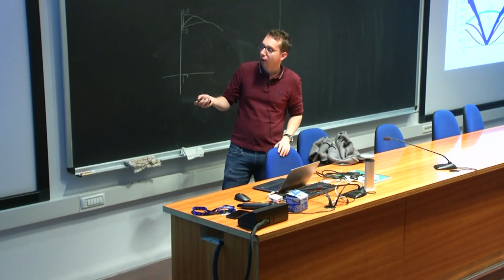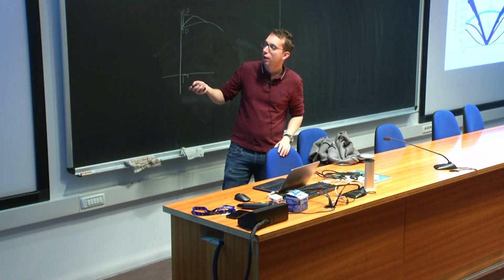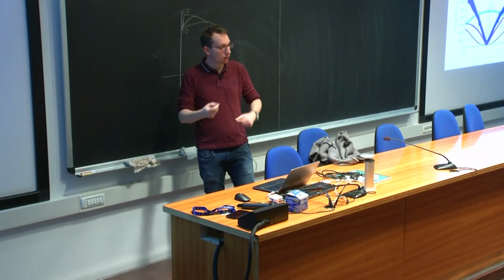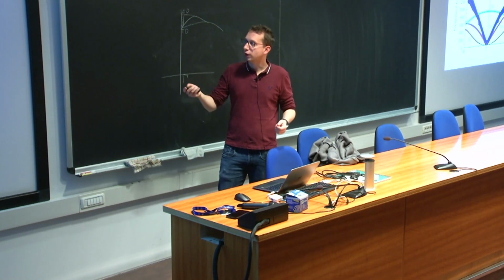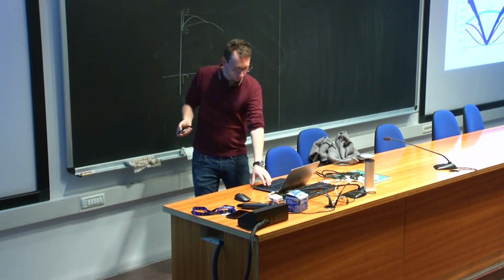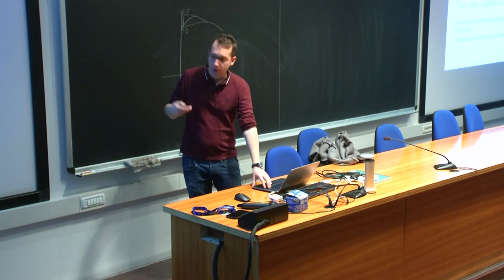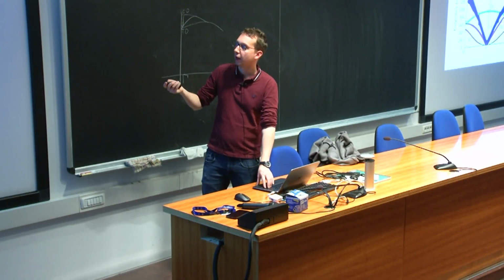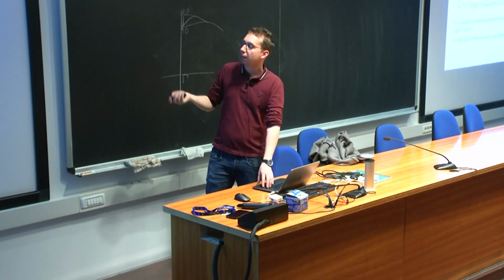And so you can see that there are no big surprises for the most part, but you have some funny places where you have strong transitions. So the phonon here has a big line width, so it means that there are two other phonons which have the correct energy and the correct momentum, and so this can decay a lot, and so on and so forth. But this is okay for a material like graphene, which is not very anharmonic.